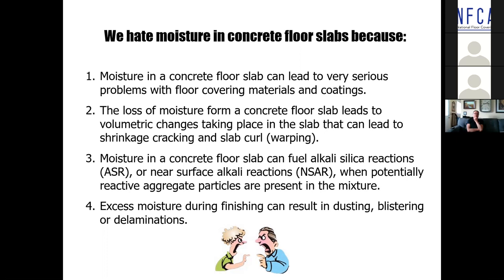So that free water occupies volume. And as that water is lost, begins to evaporate from the surface, a volumetric change takes place. Shrinkage, if you will, it can lead to cracking and to the warping or curling of a concrete slab.